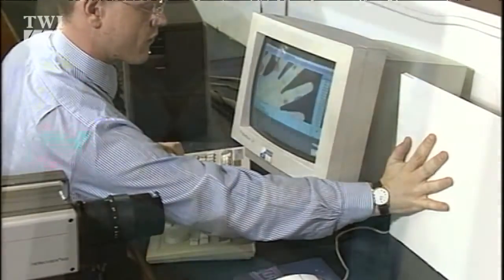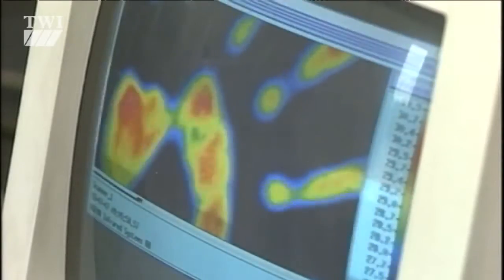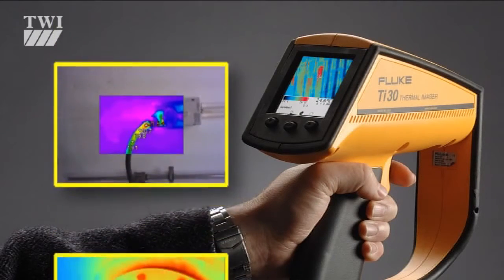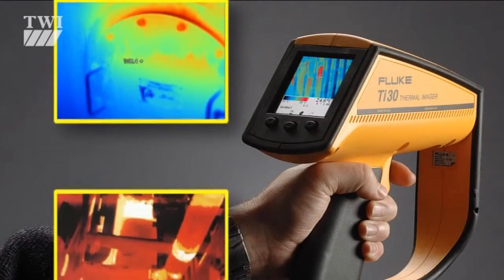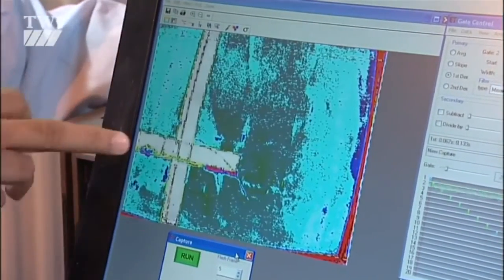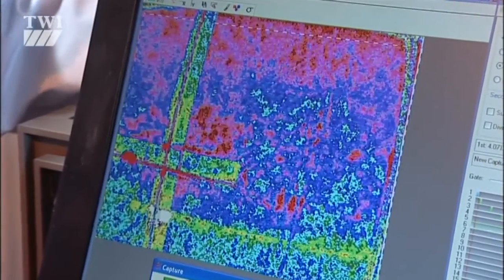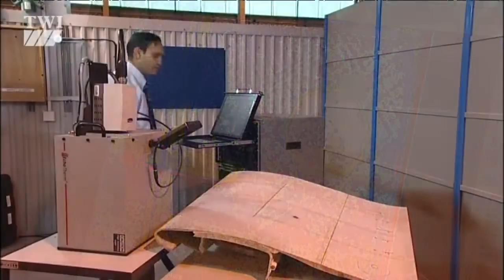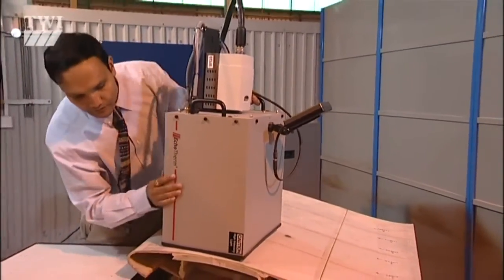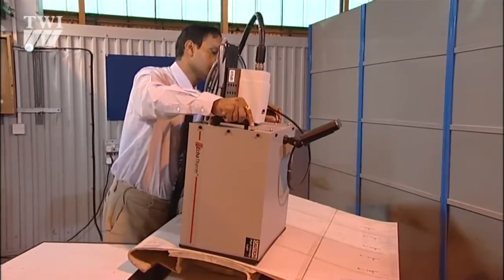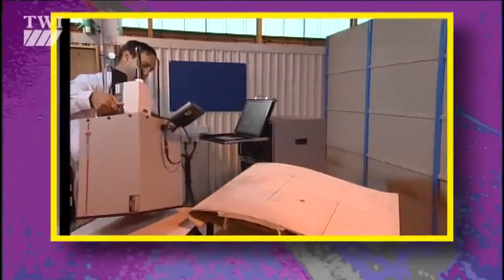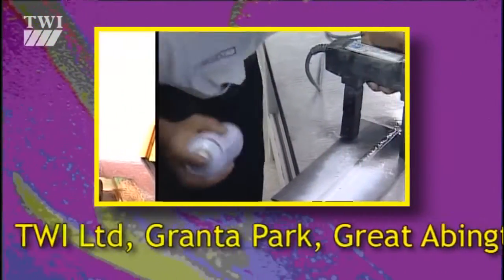Finally, thermography is the simplest of all thermal inspection techniques. It involves using an infrared camera to look for abnormally hot or cold areas on a component operating under normal conditions. Most modern thermal cameras are able to detect temperature differences of less than a quarter of a degree Celsius, and they enable thermal images to be recorded on video or computer disk for future analysis. Thermography is a remote technique suited to most areas of plant, particularly equipment operating at elevated temperatures. Active thermography, where heat is applied directly to the component, is used for inspection of low-conductivity materials like composites.